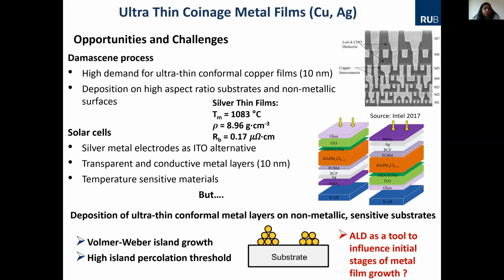And when you see, copper is a very good material, but I said the tendency with metals is that when you have a substrate, you know that the growth on different substrates of metal films is different. It can be island formation, then they can join, percolate, and form a continuous film. But then at some stage, the films become thicker, and then they are opaque. So I would like to have a film that is very thin, and then you nucleate such that you have a monolayer, and then you can have very thin layers, which at the end can be transparent as well as conducting.